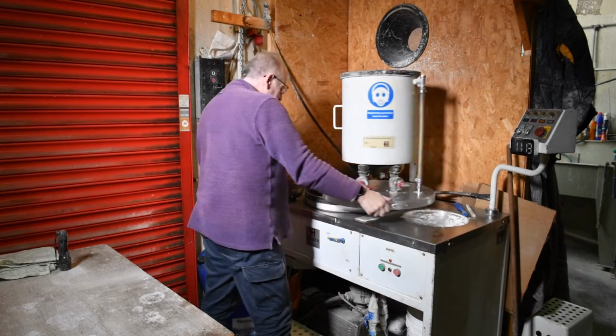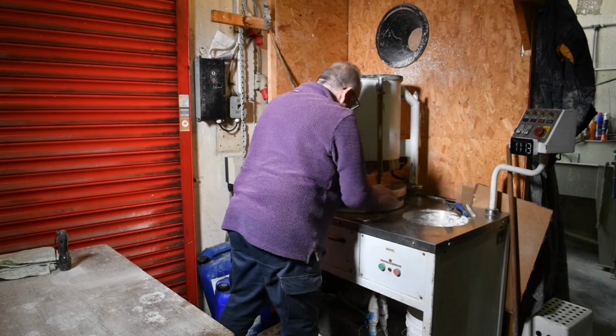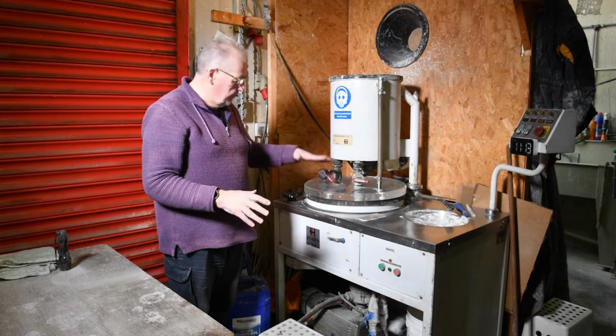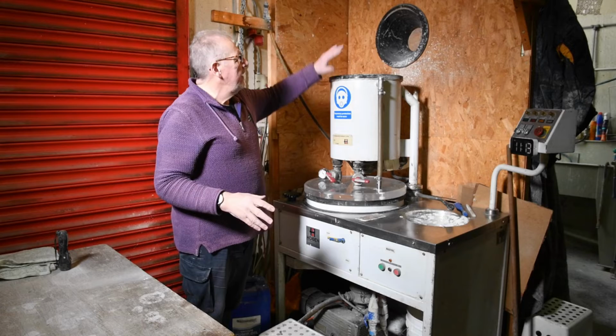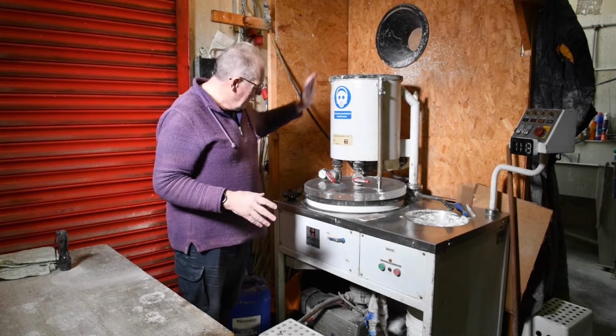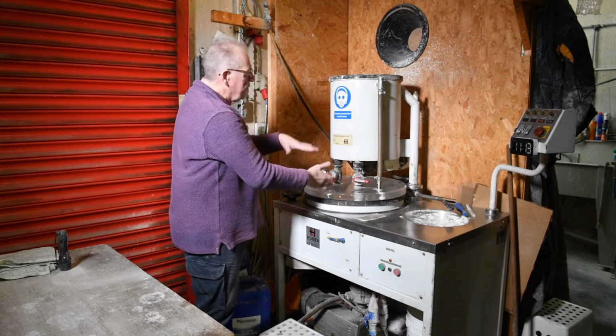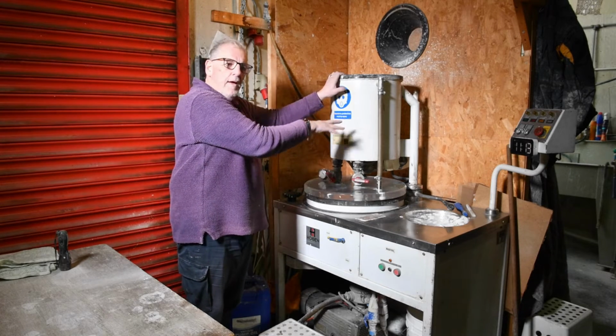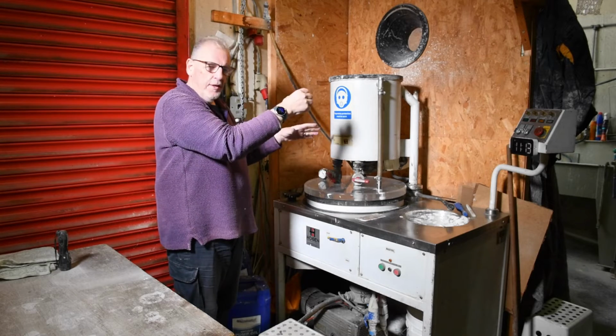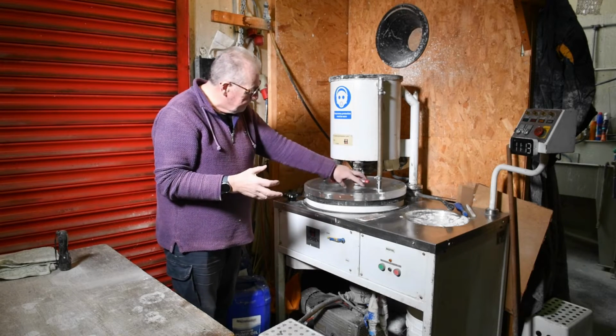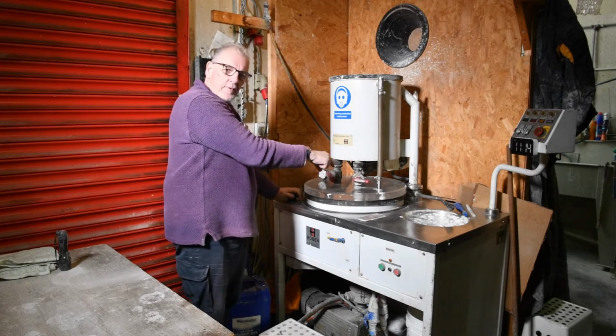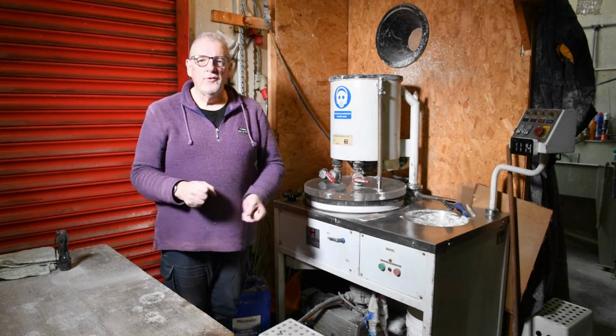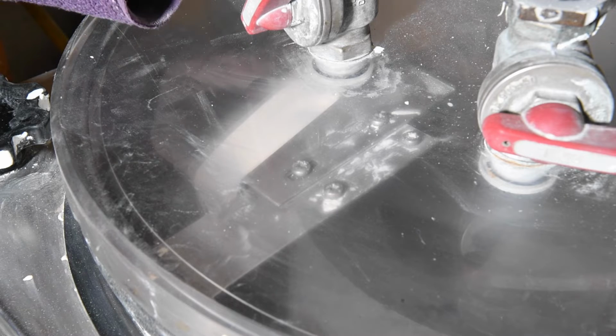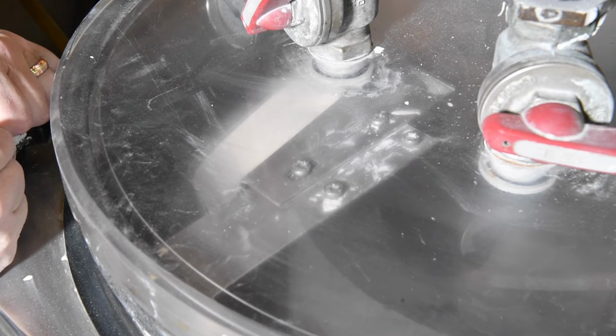Right, so we'll just swing the lid across and lower it onto the seal. So this is built up with two chambers. We've seen the bottom chamber where the flasks have gone. The top chamber is a mixing machine, effectively, and then we have ball valves between the two. Once we've put the water in, and then we add the plaster, it will mix it all under vacuum, and then we'll open the bottom valves to allow the plaster into each of the flasks, and then they will be set to one side to set. So the plaster flows and fills the flask.